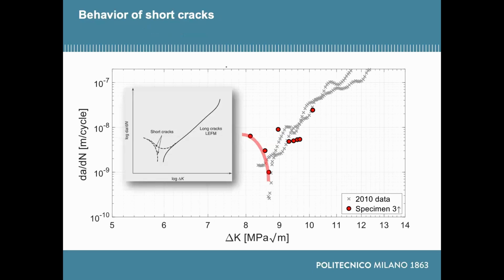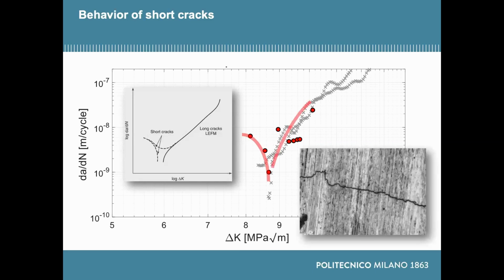The mechanism is well known. You have a long crack growth threshold here, and so you have short crack propagation, and you have a crack that is slowing down, and then it is accelerating when you increase the delta K, so the available energy for propagation. And mainly this threshold is generated by a crack that is propagating through the lamella planes, so when the lamella planes are perpendicular to the crack propagation.